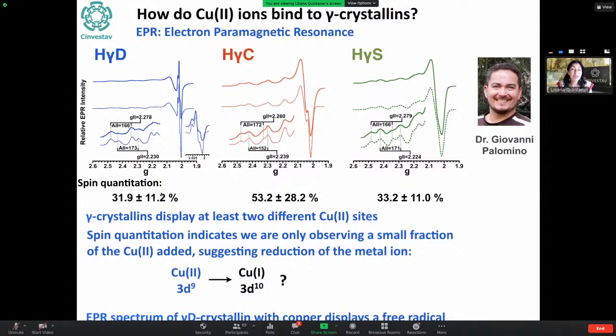I mean, with EPR, even if it's in the aggregate state, we can still see the metal ion. So he found that in all three proteins, we could discern at least two different copper-2 species bound to the protein. But something interesting came up, and that's the spin quantitation. So copper-2 is a 3d9 configuration, so it has one unpaired electron, and we can actually quantitate the EPR signal and see how much spin we have there. And he could only see 30 to 50% of the copper-2 ions that he added, suggesting, where did the rest of the copper-2 go?